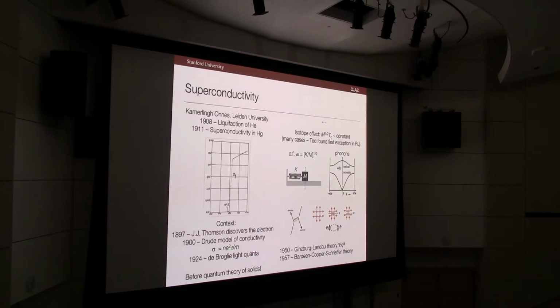And this to me is kind of interesting because at that time there were a lot of basic questions, right? So there's some phenomenological scattering time. Metals tend to get more and more conducting at low temperatures. There are big debates about what happens in the zero temperature limit. Maybe all the electrons just freeze and you become an insulator. Or maybe you go all the way to being a perfect conductor. And rather what they found was this peculiar transition, right? It turns out that they first studied platinum and found that platinum saturated with the residual resistivity. And one of the features of mercury is that it's a liquid metal at room temperature, so they could play around with distilling it and various aspects of their properties.